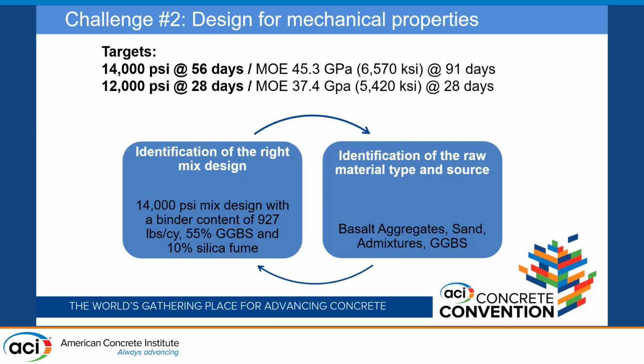During the lab trials for the development of these designs, it was determined that the local supply of stone was not adequate enough to achieve the high modulus of elasticity requirements. The design team then targeted a basalt aggregate source that ultimately improved the mix design gradation and helped achieve the elastic modulus requirements. Additionally, the workability was enhanced. Once the gradation and the modulus of elasticity were improved, the team settled on the following materials to further optimize the mix.